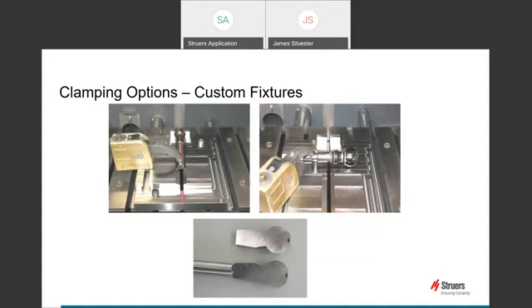As you can see from the top left image, care has to be taken during this first cut to ensure you do not cut through the clamp. The use of automated cutting options allows accurate cut length to be programmed on all of our automatic machines to ensure that this sort of mistake should not occur. Again, the use of the laser for alignment greatly assists in positional accuracy and is reflected by the quality of the result.